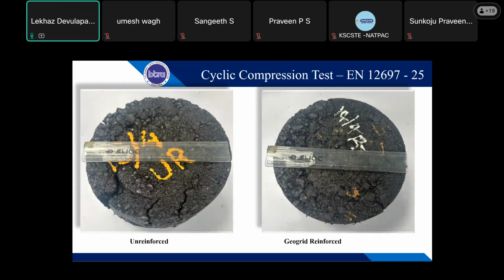And you can see the test specimen after the test. This is the unreinforced test section. You can clearly see the cracks that have formed, and there was a complete depression, with 5% or nearly 5% strain accumulated on the specimen.